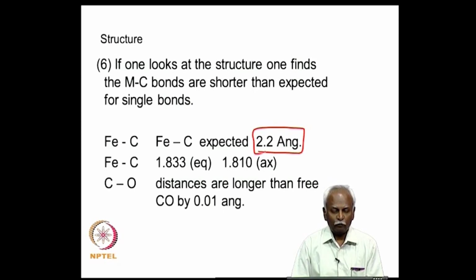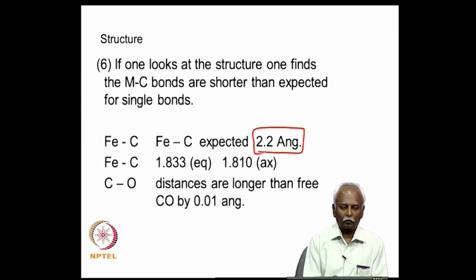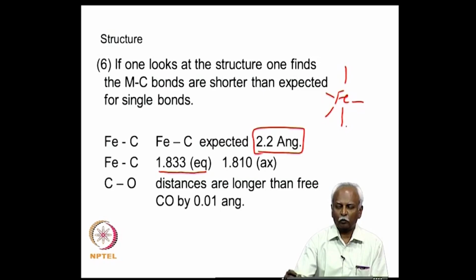But the Fe(CO)5 molecule turns out to have an iron carbon bond distance of 1.83 angstroms in the equatorial position. So, here is a molecule which has five ligands. It has a trigonal bipyramidal geometry. Each one of these lines represents a carbon monoxide. So, you have a carbon monoxide at the end of each of these lines. And so, this bond distance is what we are talking about, and this bond distance turns out to be smaller than what you expect on the basis of the single bond radius.